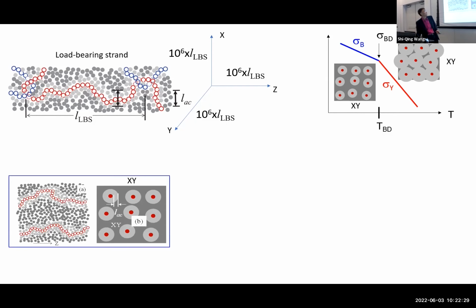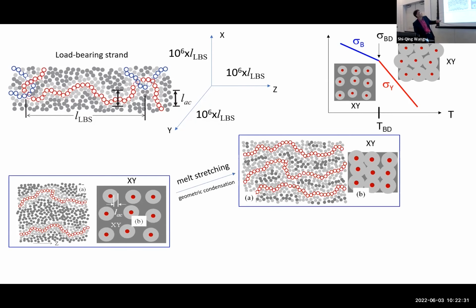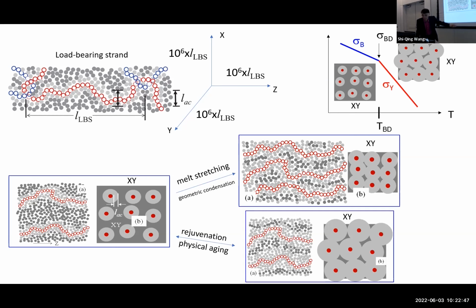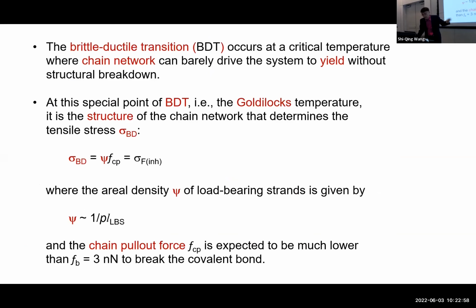Therefore, it breaks apart. So basically, this allows us to understand why melt stretching makes polystyrene ductile, something known for 50 years, because you bring the load-bearing chains closer, so your activation zone only needs to be smaller to achieve activation. And you can understand physical aging and rejuvenation in the same manner, in terms of how dormant the system is. So basically, we can understand it.